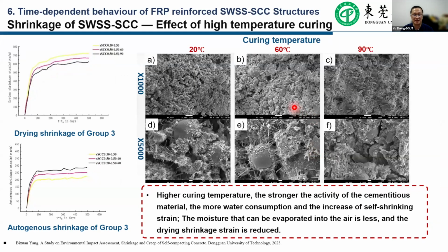Furthermore, when we increase the curing temperature for the seawater and sea sand self-compacting concrete, it can increase the secondary hydration of the fly ash and speed up the hydration process. Therefore, the strength is increased. At the same time, the shrinkage of the specimen under high temperature curing enters the stable period 20 days earlier than that of the ordinary specimens.